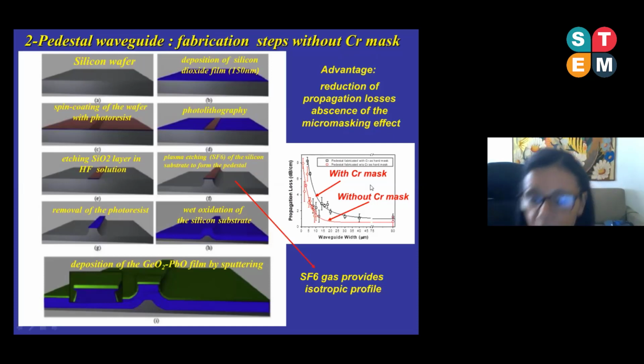As a consequence, we have this interesting result that shows the propagation losses in 2 different conditions: when we use the chromium mask and when we do not use it. And we can see clearly that we have a reduction of the propagation losses, and this represents an interesting advantage that in fact increases the waveguide performance.